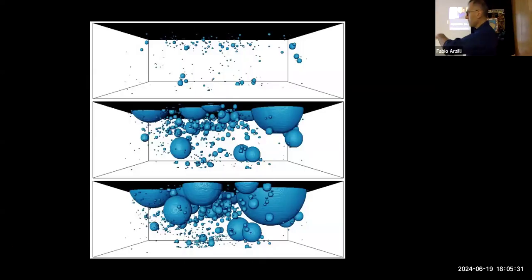And so we performed this. You can see the evolution of bubbles through time. This is a few seconds from the beginning to the end, about 20 seconds more or less. The difficulty was to control pressure with the piston. Moving the piston up and down, we produced some decompression, but we were not able to track exactly what pressure was imposed.